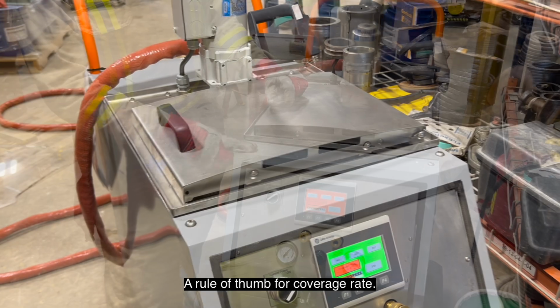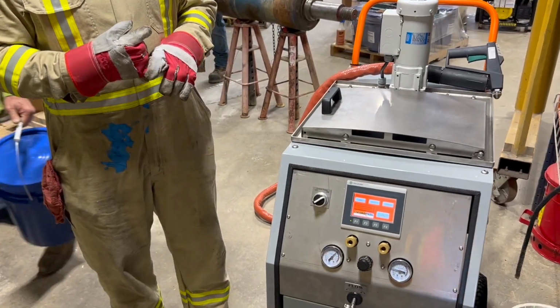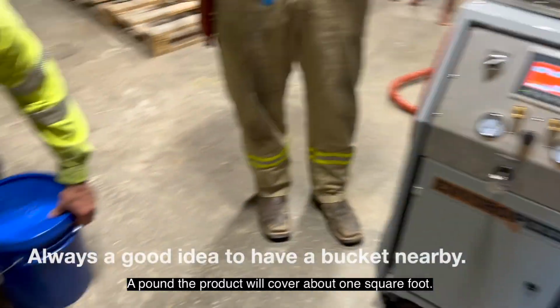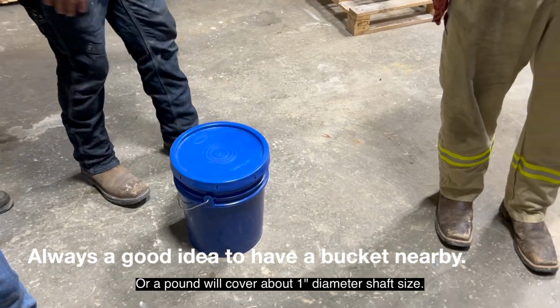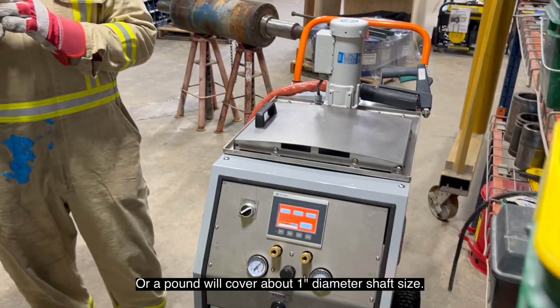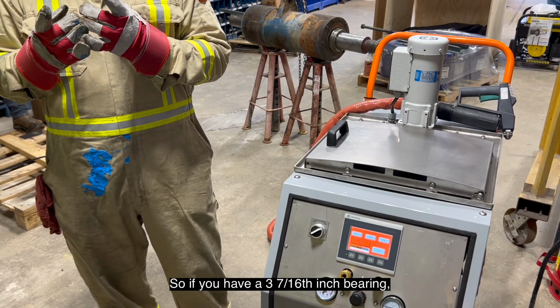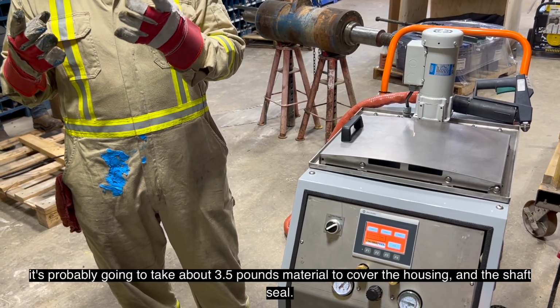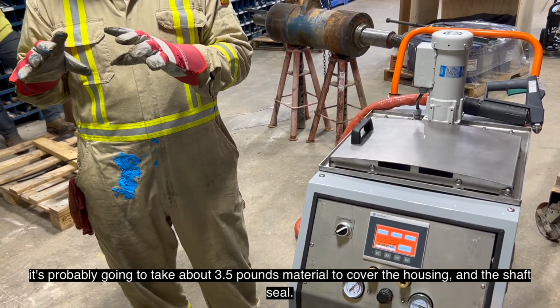Rule of thumb for coverage rate: a pound of product will cover about one square foot, or a pound will cover about 1 inch diameter shaft size. So if you have a 3 7/16 inch bearing, it's probably going to take about 3.5 pounds of material to cover the housing and the shaft seal.